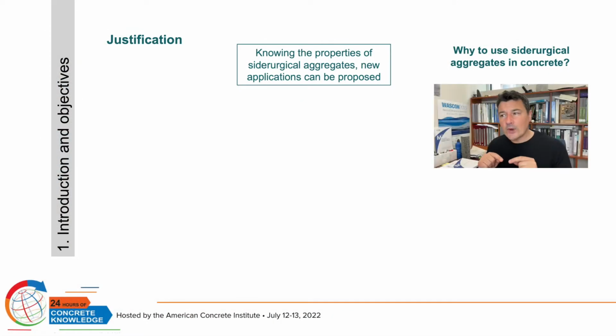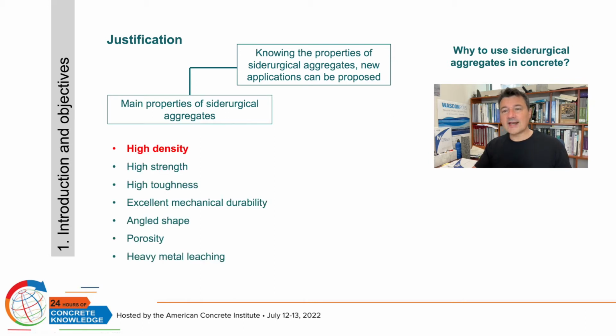So first, we are going to determine the properties of these siderurgical aggregates. What are the main properties? First, the high density. The typical density of a siderurgical aggregate is higher than 3 grams by cubic centimeters, but it presents high strength, also high toughness, and excellent mechanical durability. The shape of this material is very interesting in order to increase the bond between the aggregate and the cement paste. Also, depending on the method to produce the siderurgical aggregates, it can be present porosity and also sometimes heavy metal leaching.